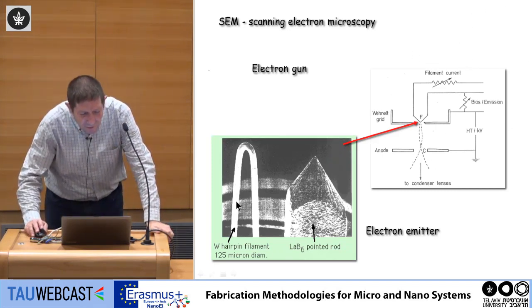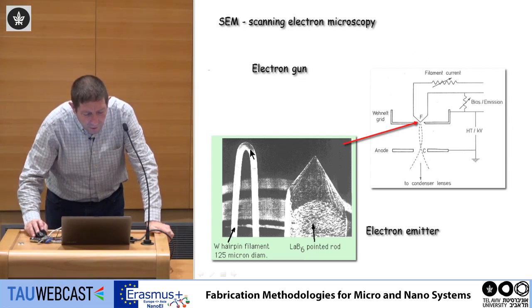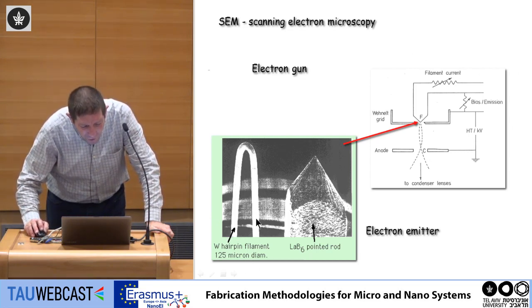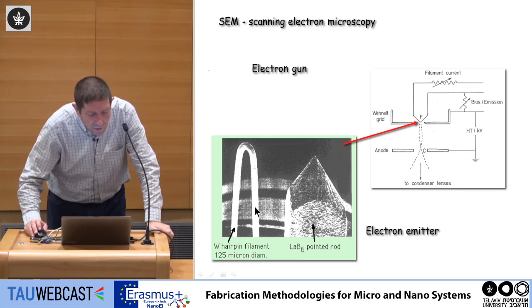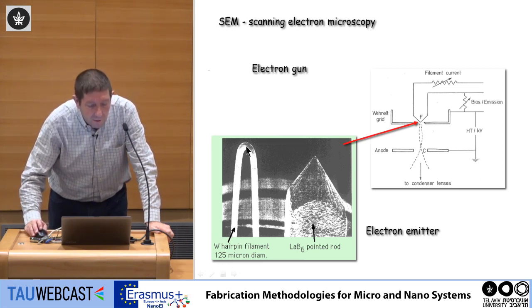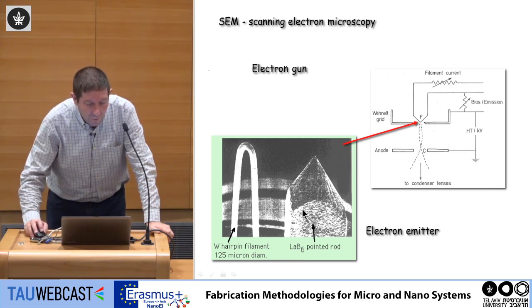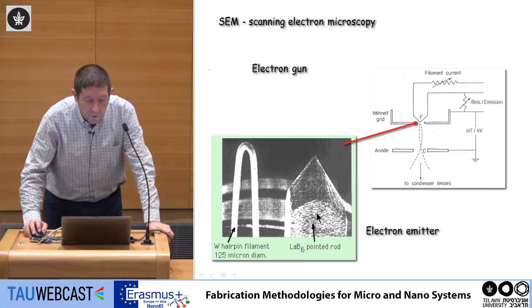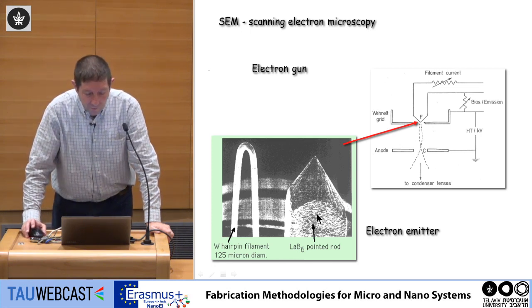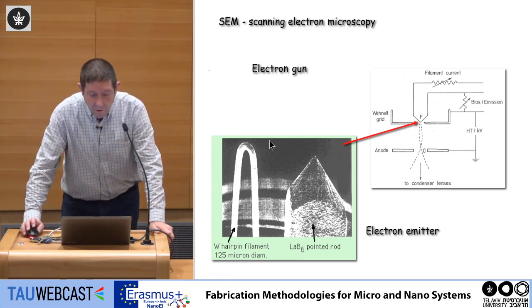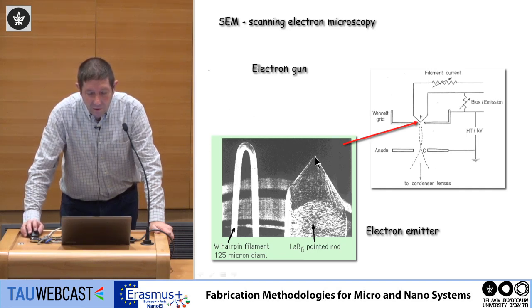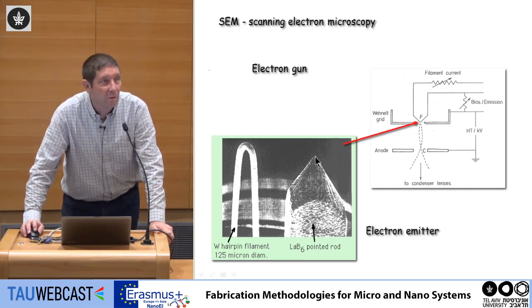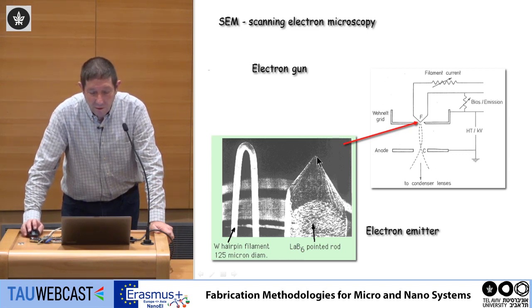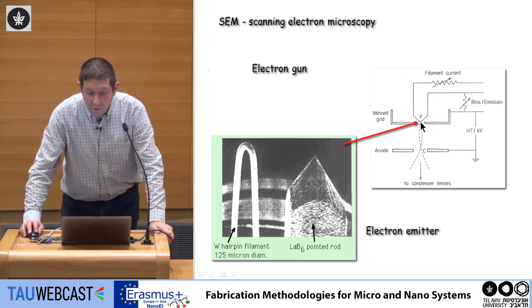This is a tungsten hairpin filament, with a 125 micron diameter. You pass current through this filament, and then you get emission of electrons from the tip. Or this is another very common gun, which is called lanthanum hexaboride. And the nice thing about this material is you can get very, very sharp tips. Because you have very sharp tips, the emission here is more monochromatic and more effective. And you heat this up, and electrons are emitted.